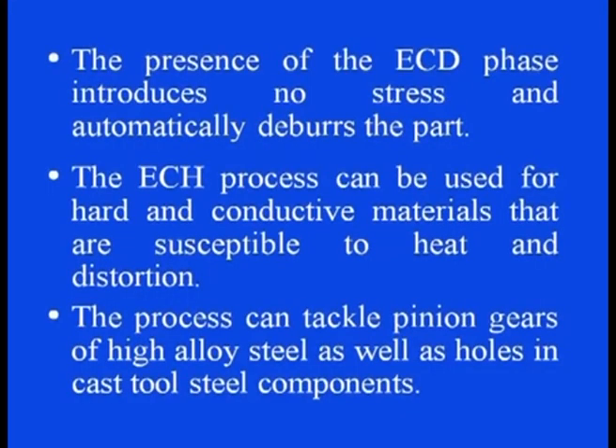The presence of the electrochemical dissolution phase introduces no stress and automatically deburrs the part in this process. The electrochemical honing process thus can be used for hard and conductive materials that are susceptible to heat and distortion. The process can tackle pinion gears of high alloy steel as well as holes in cast tool steel components. Hone forming is another application that combines the honing and electro deposition process. It is used to simultaneously abrade the work surface and deposit metal. The method is the reversal of electrochemical honing in basic principles.